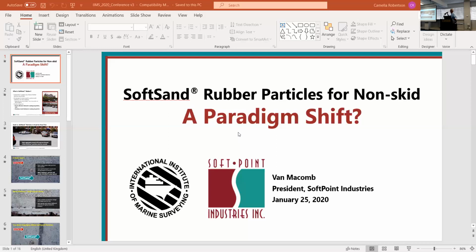So this is just a close-up of that parking deck I showed you earlier. It's a nice small deck, so it's a nice little test area. We used both the sand aggregate that they had been using over the years, and we also used the soft sand. In this case, we used white soft sand particles, so we'd have a contrast over the gray coating. And you guys can obviously see where I'm going. I view a deck's a deck, whether it's a concrete deck or a steel deck. The coatings are very, very similar. So this is the history where we got started.